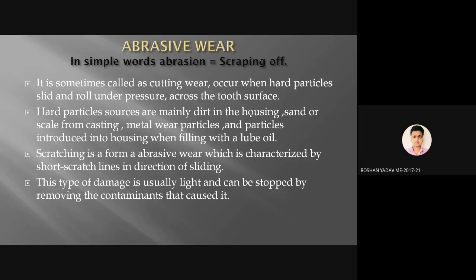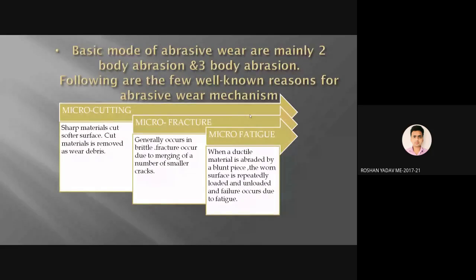Basic modes of abrasive wear are of two types, two-body abrasion and three-body abrasion, which was covered by the other group, so we won't go into much detail about that. Following are a few well-known abrasive wear mechanisms. Micro cutting: a sharp material cuts a softer surface, and the cut material is removed as wear debris. Micro fracture generally occurs in brittle materials, where fracture occurs due to the merging of a number of smaller cracks. Micro fatigue: when a ductile material is abraded by a blunt piece, the surface is repeatedly loaded and unloaded, and the failure occurs as fatigue.